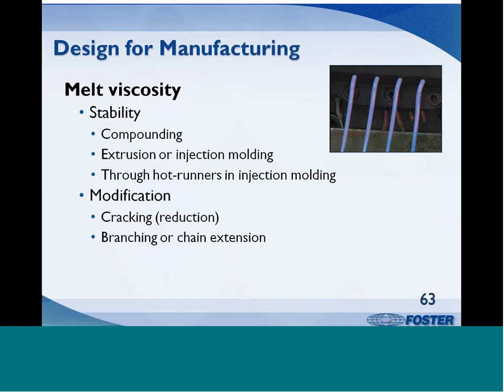In order to maintain a stable melt viscosity, antioxidant and thermal stabilizers should be added at the compounding step to make up for those that will be lost with each additional thermal history. Injection molding through a hot runner system can be especially brutal on a resin stabilizer system.